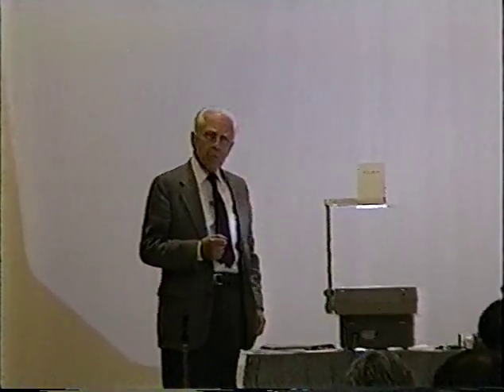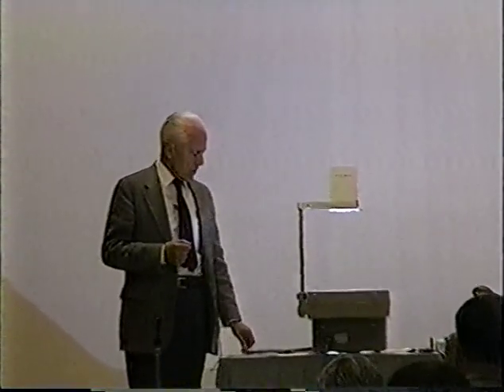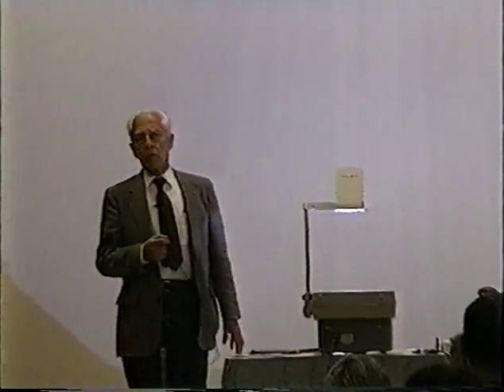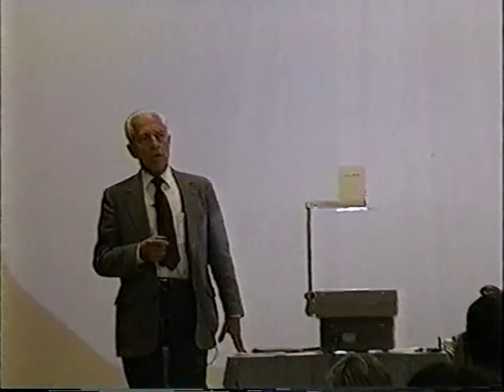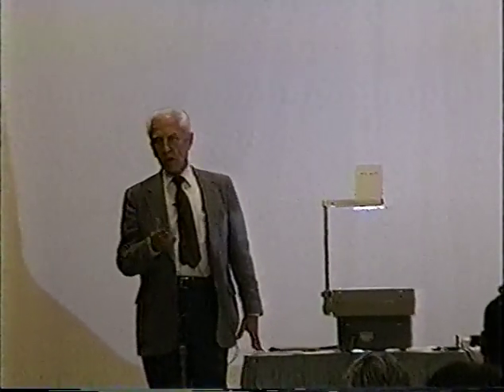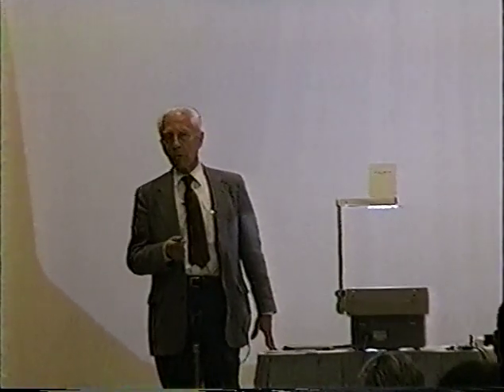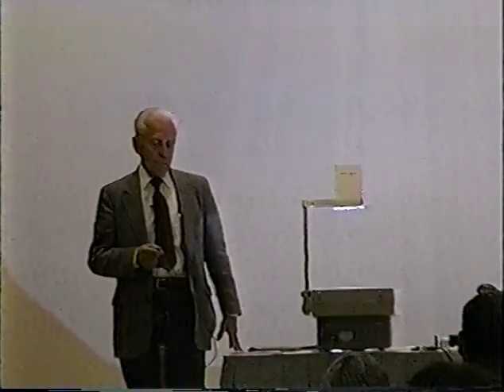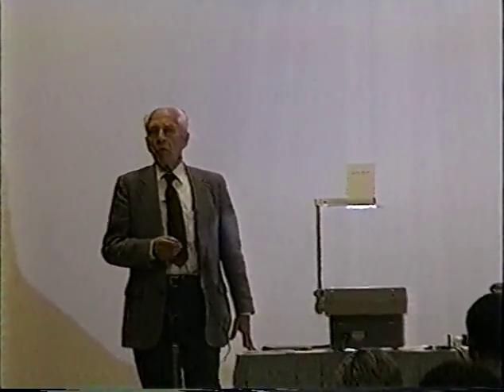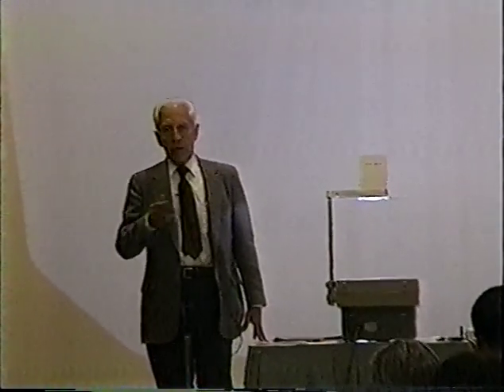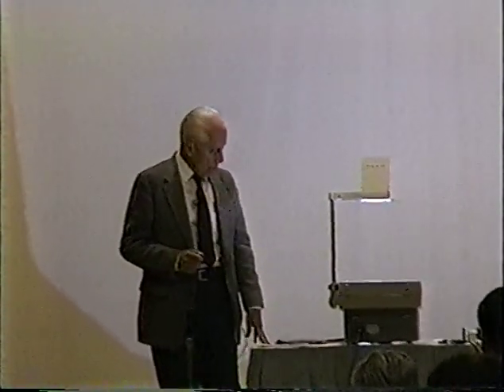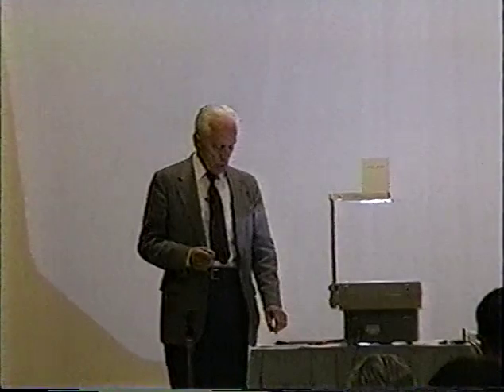So the first experiments that I performed, exploratory sort of experiments, were done with an isoperibolic calorimeter in which the operating signal was a temperature rise by a thermocouple, a chromel-alumel thermocouple. And indeed, every now and then I thought that I observed excess power based on the calibration curve. But I could not have any confidence in these results.